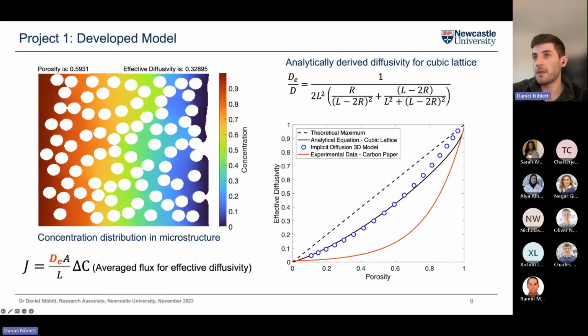And now this red line, which I've also plotted on there, that's actually the effective diffusivity for carbon paper material, which is used in many electrochemical cells. And as you can see, this type of cubic lattice is actually a couple times higher than the traditional materials. So if we can optimize the material, we know that the lattice type structures should do reasonably well.